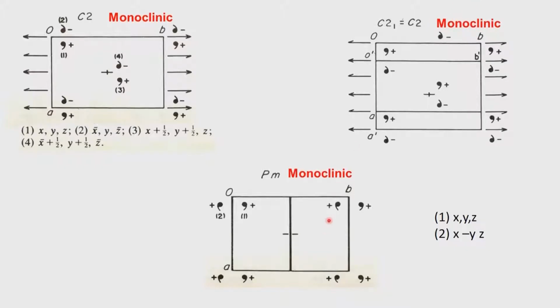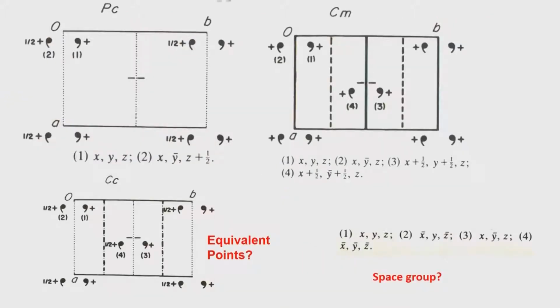Then we introduced the next symmetry elements. After the point group symmetry 2, we have the point group symmetry m. We looked at the monoclinic symmetry primitive, and then we went further and looked at the monoclinic symmetry Pc, with P the primitive and c the glide plane. So, then we looked into the mirror symmetry operation with respect to the C centering, and then we had arrived at this point where we had the Cc.